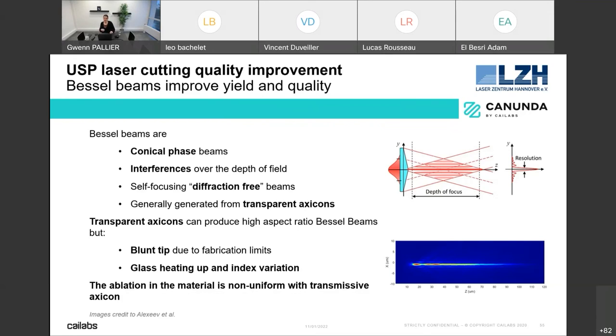When you want to do that with a transparent axicon, you have drawbacks, mainly due to the blunt tip. When you are manufacturing your axicon, the tip is always a little bit round, and this is adding a spherical wave. So you have your conical wave plus a spherical wave from the center of the axicon. When all this is making interferences, it makes oscillation over the Bessel beam. So you are above the threshold, below the threshold, above the threshold, below the threshold. And this is not good when you're doing cutting. Another big drawback is that glass is heating up, so the index of the glass is varying. And this is again not good because you are modifying the pulse duration and the quality of your beam.